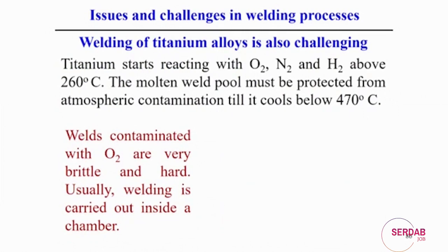Another issue of the welding process is that welding of titanium alloy using the normal arc welding process is really very challenging, because at high temperature titanium always reacts with oxygen, nitrogen and hydrogen, and the molten weld pool must be protected from this atmospheric contamination until it cools down to a certain temperature. So, that is a real problem. It may not be too severe in the case of welding steel, but welding titanium is very difficult, because it easily reacts with oxygen and hydrogen, and the oxygen becomes part of the final weld joint. So, the weld can be contaminated with oxygen, and it actually becomes very brittle and hard.